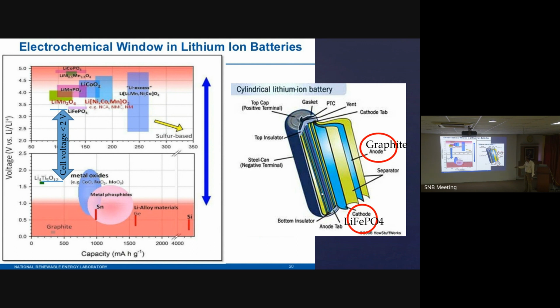And graphite is also in the red line, but graphite is protected by the solid electrolyte interface, which is a protective layer. When the graphite reacts with the electrolyte in the first cycle, it forms a lithium carbonate kind of material, called SEI, and it protects. But if the battery starts getting heated up, that SEI goes away and it becomes reactive, and that makes the battery fragile. So now we choose this, and there is another material called lithium titanate, which is a very robust material for all temperatures and charges very fast, but is more expensive than graphite.